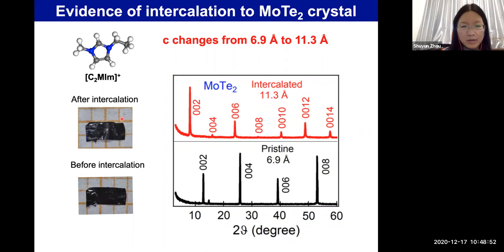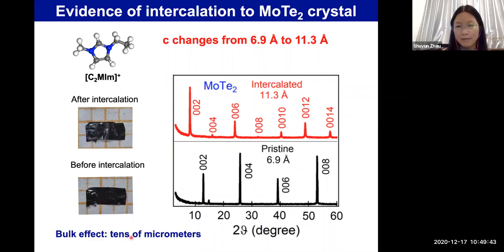Here is the sample that we use to intercalate. This is a single crystal, 3 millimeters by 1 millimeter by about tens of micrometers. After intercalation, we can check the X-ray diffraction data, and we see that the original peaks from the pristine molybdenum ditelluride sample are all gone. Now we have a new set of X-ray diffraction peaks with an interlayer spacing of 11.3 angstrom. So this intercalation changes the interlayer spacing from 6.9 angstrom to 11.3 angstrom. And this effect is bulk sensitive. It applies to the entire bulk single crystal.